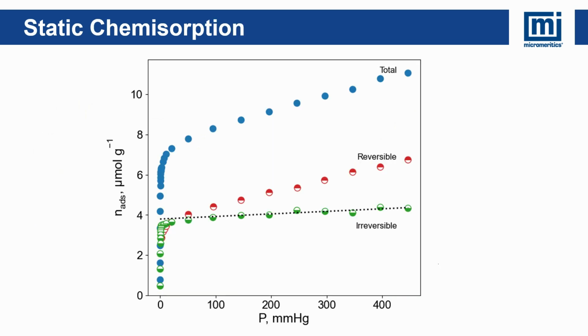Today's webinar will focus on two of the most commonly used methods for determining the metal dispersion of catalysts, static and dynamic chemisorption. The probe gases typically used are carbon monoxide or hydrogen. Let's begin with static or volumetric chemisorption, a method you may be familiar with. In a static chemisorption experiment, it is crucial to ensure that the sample has a clean surface before performing any analysis. For this webinar, we will use our standard reference material, the platinum-alumina catalyst, and carbon monoxide as a probe gas.